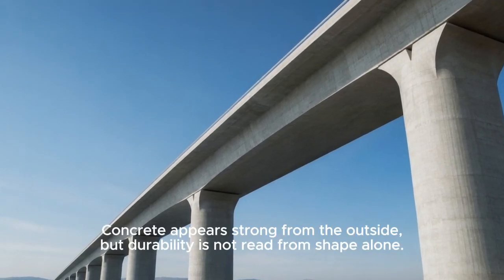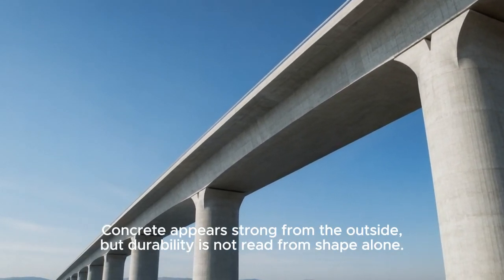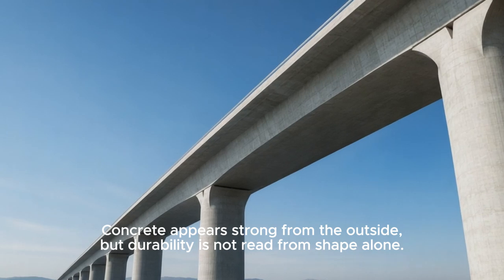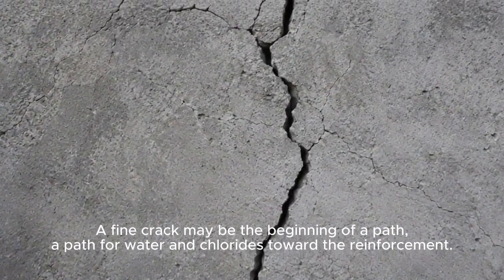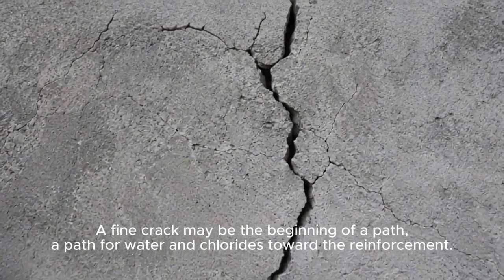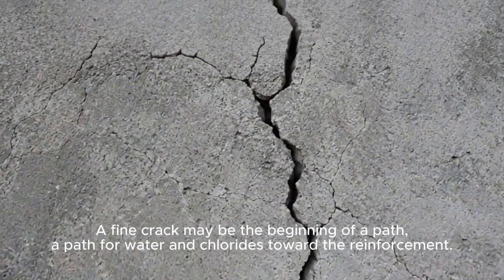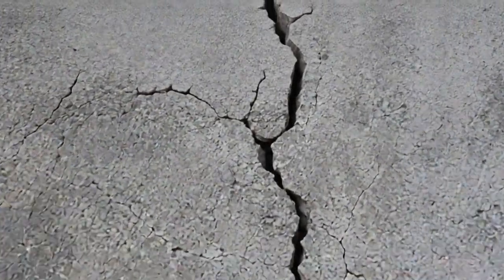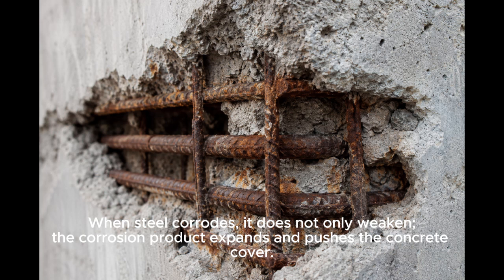Concrete appears strong from the outside, but durability is not read from shape alone. A fine crack may be the beginning of a path for water and chlorides toward the reinforcement. When steel corrodes, it does not only weaken, the corrosion product expands and pushes the concrete cover.